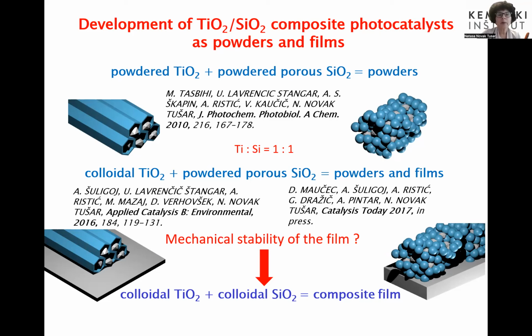We combined powdered titania and powdered porous silica. We combined SBA-15, and also disordered silica, as I mentioned before, KIL, and we discovered that the best performance happens if we have a molar ratio of titanium and silicon 1:1. Later we also combined colloidal titania and powder silica, and now recently colloidal titania and colloidal silica. Mainly, when we made different films, different coatings on glass carriers, we used glass carriers and also aluminum carriers. We discovered that the mechanical stability of the films is very poor.